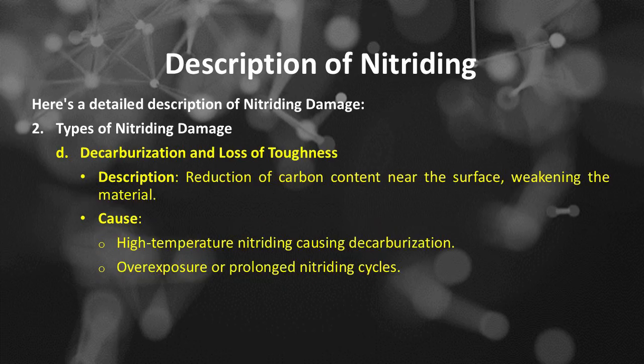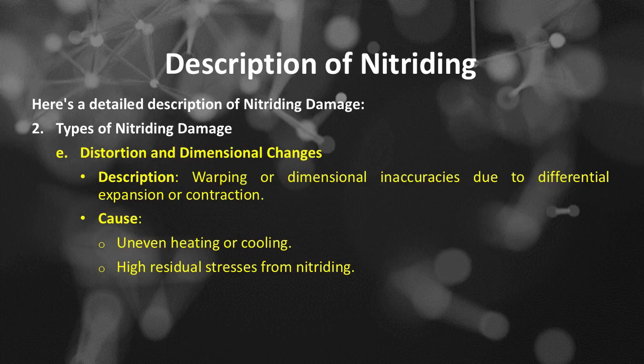Types of nitriding damage. D, decarburization and loss of toughness, described as reduction of carbon content near the surface, weakening the material. Causes include high-temperature nitriding causing decarburization, overexposure, or prolonged nitriding cycles. E, distortion and dimensional changes, described as warping or dimensional inaccuracies due to differential expansion or contraction. Causes include uneven heating or cooling and high residual stresses from nitriding.